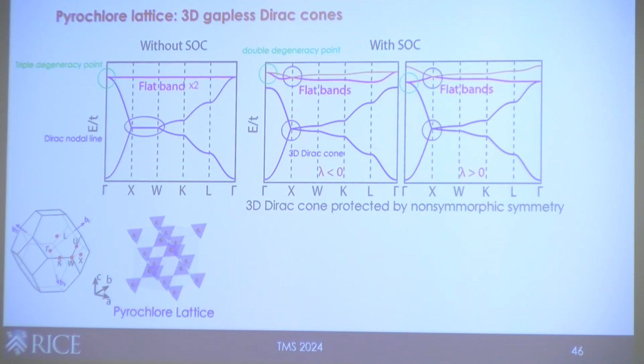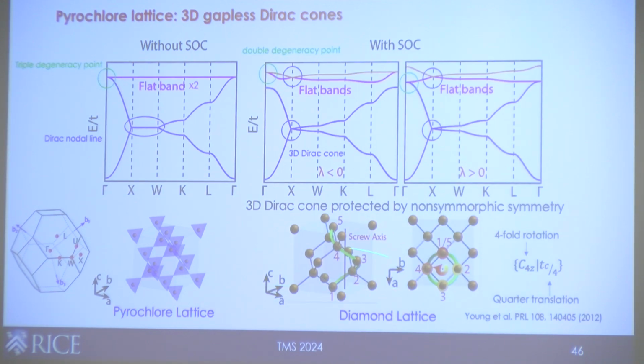So if you remember the construct that Stephen showed about the relationship of the Kagome lattice to the honeycomb lattice, you can do a similar thing for the pyrochlore lattice. These are the tetrahedra for the pyrochlore lattice. If you consider the middle of each of these tetrahedra, those sites will give you a diamond lattice. Just like if you do this for the Kagome lattice, you end up with a honeycomb lattice, right?